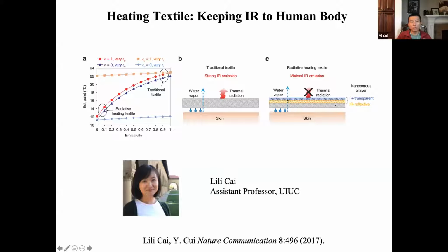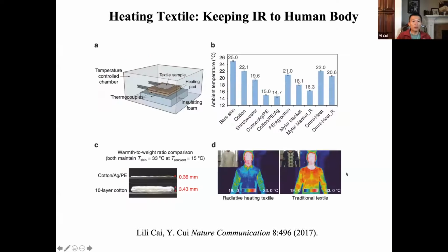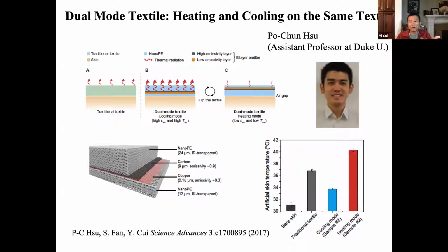So we have these nanoporous materials embedded into a textile, and also external surface needs to be low emissivity as well. And really demonstrated we have a really good warming effect. So I won't go into detail of all this data. And it's also possible, you could do bifunctional, tuning the emissivity outer surface high or low by wearing this textile inside out. You could have a difference of a wearing experience. If environment temperature change, wearing your clothing inside out, you have a cooling mode and a heating mode showing up. The delta T difference, through simulation we see can go up to about 9 degrees Celsius difference, and experimentally we show we can achieve 5 degrees Celsius difference right there.